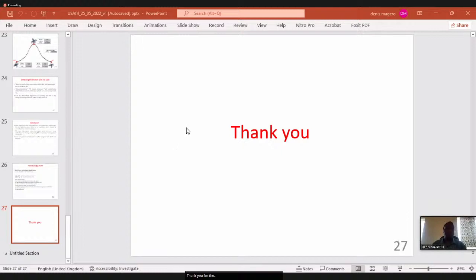Thank you, Anne, for the question. Actually, for the calculations, all of them are being done in gas phase. The reason is that when you are developing luminescence index 1, luminescence index 2, and also luminescence index 3, all the calculations we did in gas phase. If you do it in solvent, the problem becomes more complicated because factors come in, for example the rate constants and so on that you have to consider.